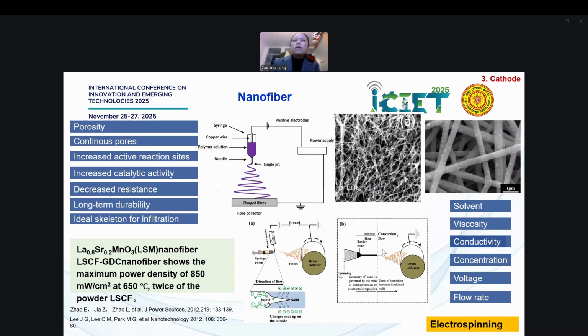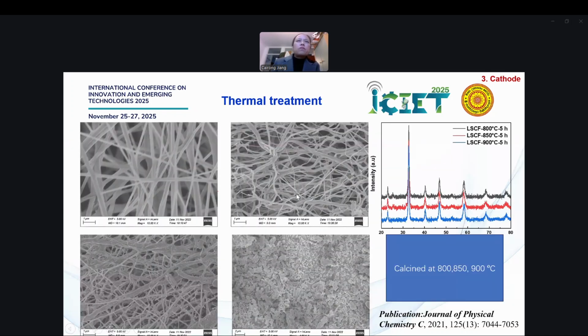So we've done these parameters on the viscosity, and tested the conductivity of the solvent, and tested the concentration of the whole solution. We investigated all the voltages we applied and all the flow rates we spread on the collector. So after all this research on electrospinning, we've got good nanofibers.